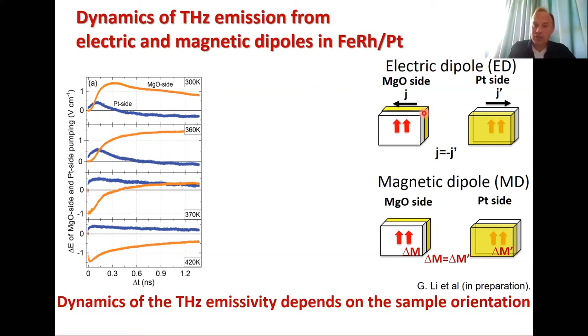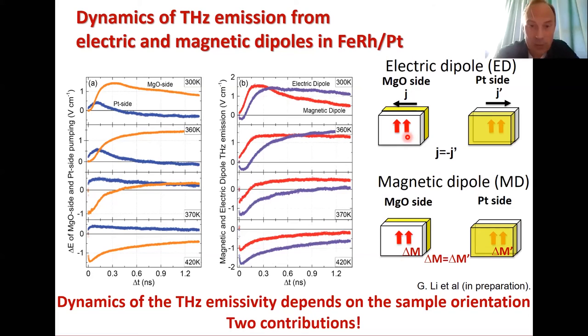The electric field of dipole terahertz emission does depend on the side from which we pump the sample. And if you talk about terahertz emission of magnetic dipole origin, you turn the sample around, and of course the change of the magnetization induced by the pump will not change. So basically, performing experiments from both sides, we either have a situation when the two sources interfere constructively or destructively. Based on this, we could extract the terahertz emissivity of electric dipole origin and of magnetic dipole origin. You can see here that in the case of experiments above the temperature of the phase transition, we have a very fast decrease of the signal already at zero delay, and then slow recovery.